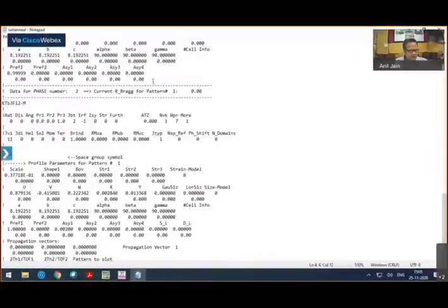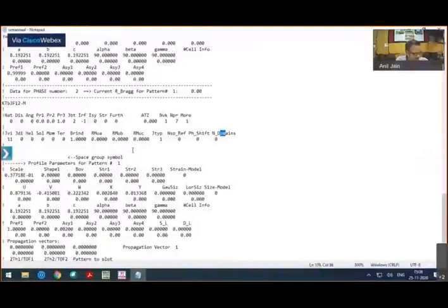To add this phase, we have added this information just before the last line in the PCR file. Now, in this phase, we are not giving any information about the atoms. The idea is to get the integrated intensity of the magnetic reflections. So I have added this phase, and now I would like to mention the important parts of it.